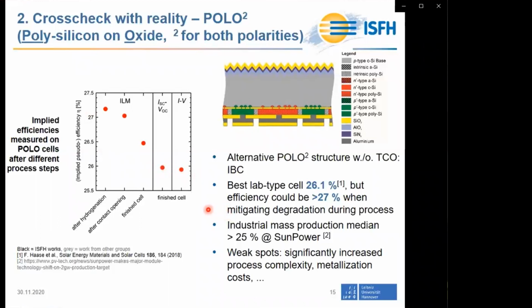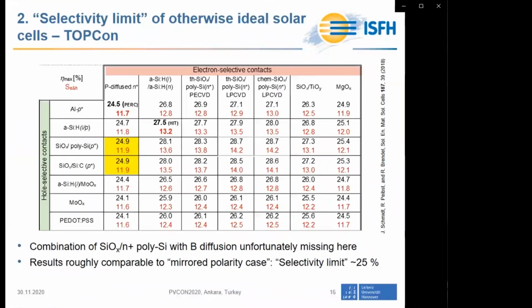Regarding mass production, one has to acknowledge that, for example, SunPower is producing similar cells with a median efficiency above 25%. And also LG is producing very similar solar cells. The weak spots of this technology, of course, are that the process complexity is significantly increased as compared to a PERC cell. Okay, let's move on with the combination of a polysilicon oxide junction with a conventional diffused junction.